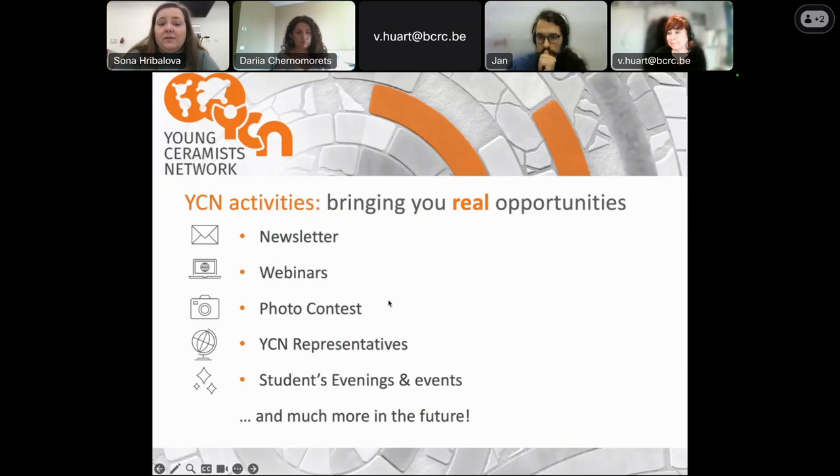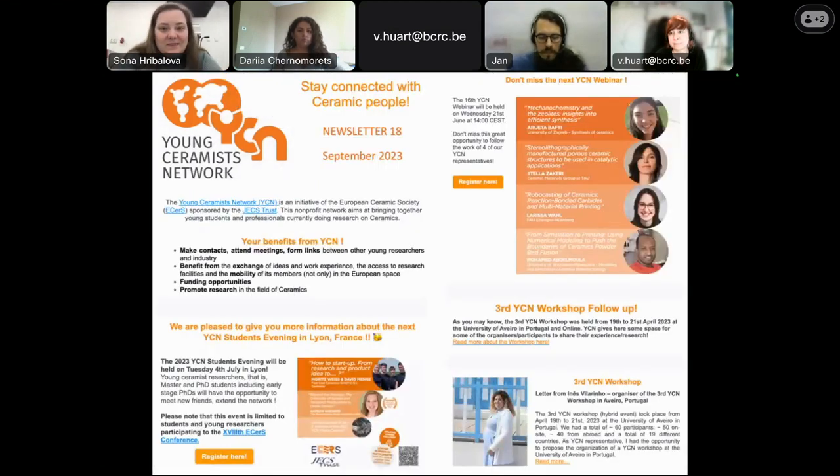And this is where I'd like to introduce the difference between transparency and translucency. There have been quite a few attempts to quantify that. One very nice one is by one of the matadors, maybe, of transparent ceramics, Professor Krell, who wanted to define that as, okay, if the material reaches 95% of the theoretical transmission, then it is transparent.